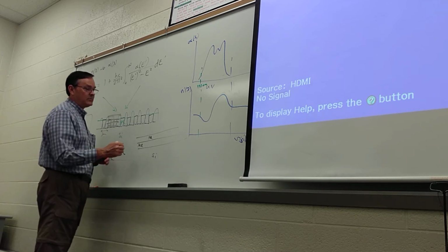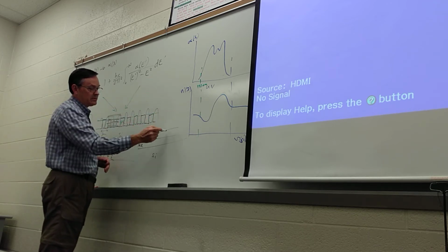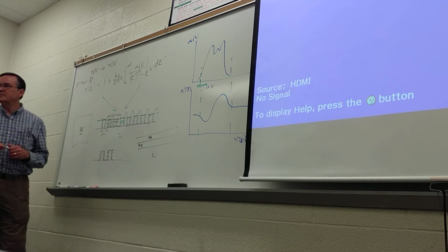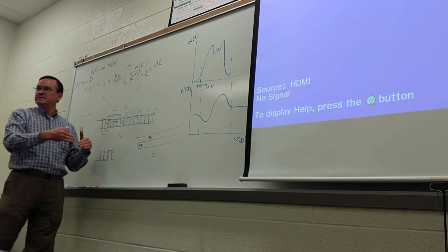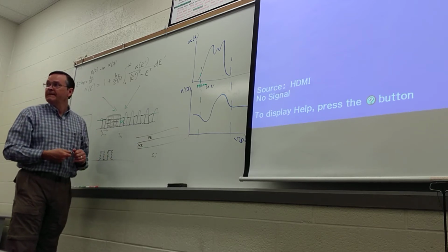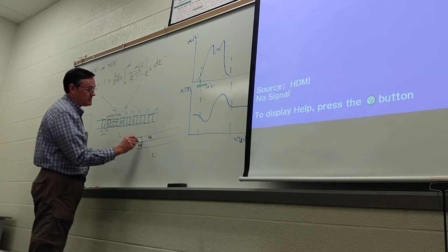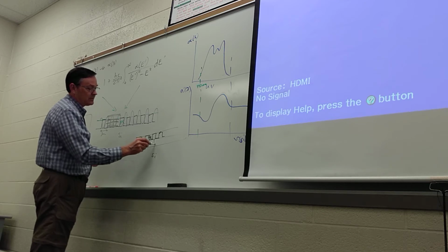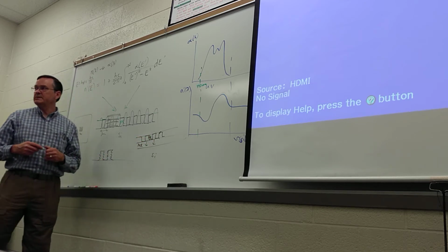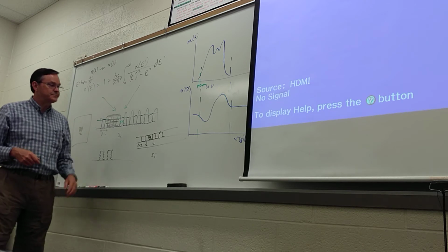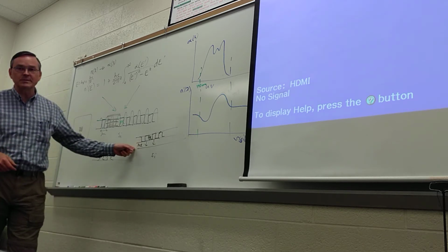Now what happens is, you bring your two beams in, you get interference here, and the purpose of the ARC layer was to absorb the light that's incident so you don't get any reflection from the silicon. After you develop, you get this in your photoresist, and now you've got to transfer the pattern through the ARC and then through the silicon. So we needed to know the absorption spectrum of the ARC, and we needed to know its refractive index. So this is what we did.